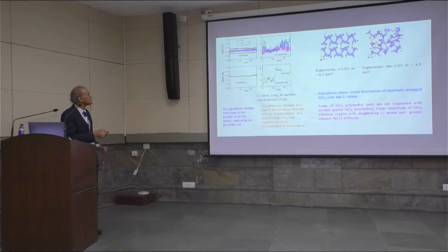Okay, if I just pick up one atom and see how its root mean square displacement is changing with temperature, then in crystalline material it is a constant. Here, this is the displacement from the original position. You can see that it shows some variation, then it shows a jump. So this is like jump dynamics. Whereas in amorphous material it is more a mix of jumps as well as a liquid-like continuous process. So this is a microscopic understanding.